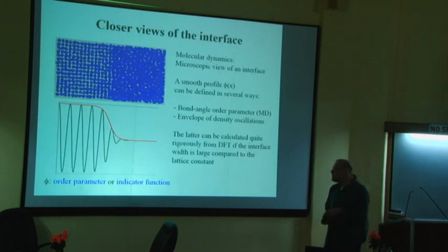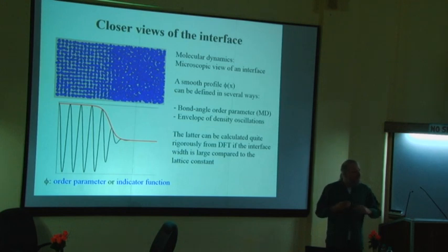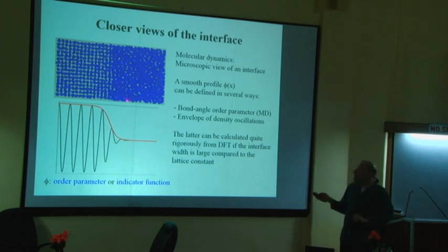Yes, because as physicists, precisely we know that this description of interfaces by sharp surfaces is a macroscopic point of view. But you can look at interfaces at various scales. And so if you look at it really at the atomistic scale, here, as promised, is a molecular dynamics simulation of a solid-liquid interface. This is a three-dimensional sample, but it has a few atomic layers thickness.